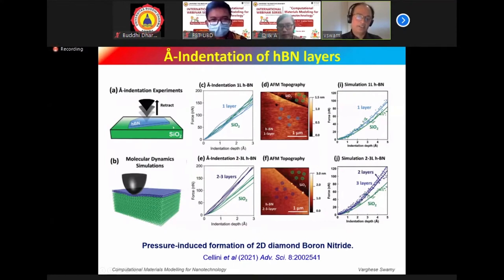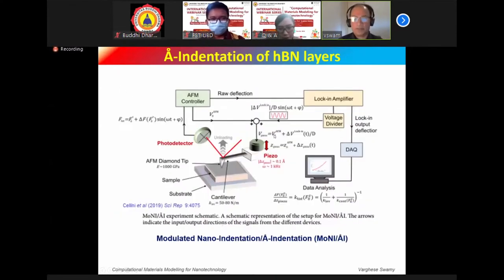If you take the one layer case, you can see that the effective modulus, this is the force versus indentation depth, is similar to that of silica, which means the silica substrate that's used here is contributing to the modulus. So this is the one layer case shown here, force versus indentation depth. Whereas when you go to 2 to 3 layers, there's a big increase in the stiffness or the resistance to indentation. That tells you that there is something happening in the material, in the two layers lying on top of the silica. So the effective modulus increases. And if you increase the number of layers up to 10, again, it doesn't show that kind of an increase. So what might be happening? This is the experimental setup that I was talking about that they use.